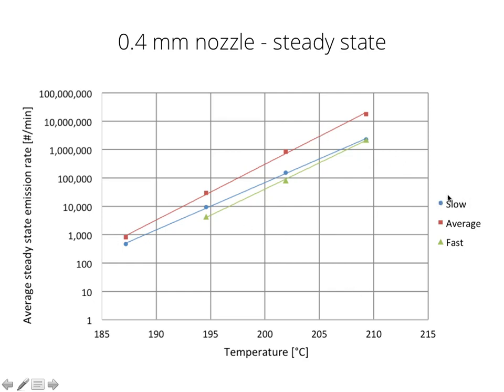So the slow one was, just to remember, 30 millimeters per second, 60 millimeters per second, and 90 millimeters per second. We can see here that the average printing speed of 60 millimeters per second is our highest particle emitter, while the fastest printing speed is our lowest particle emitter. And these are not linear functions, these are exponential functions, since the y-axis is logarithmically plotted. And as you might have already seen, the particle emissions per minute do not even closely resemble those that were mentioned in the articles before.